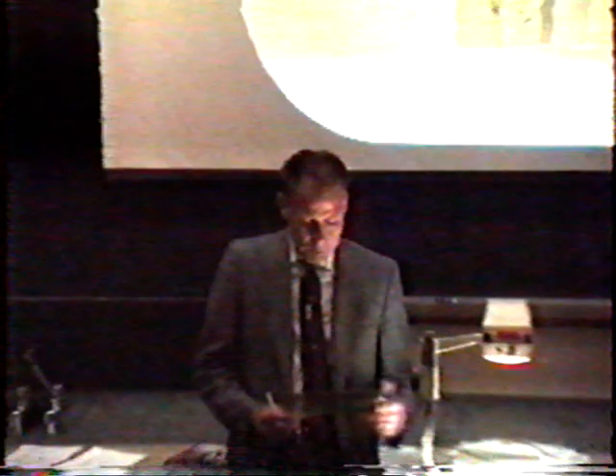We coiled the counter-electrode quite symmetrically around it. And so we had the palladium sitting inside the coil, and the coil was fairly uniform. We kept it as uniform as possible about the palladium. When we went to this design, then after 6 to 8 days, we started seeing excess heat. It took about that long to load up and get the deuterium fully loaded with the palladium. But after 6 or 8 days, we started seeing excess heat effects that were as large as 30% more heat coming out than we were putting in.